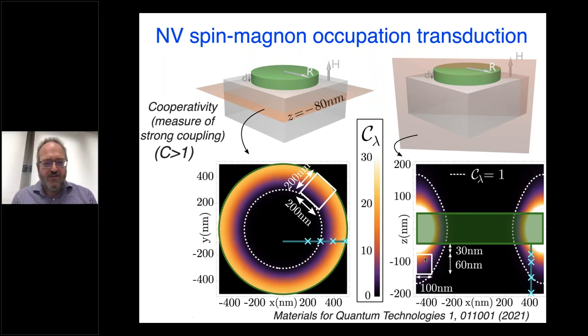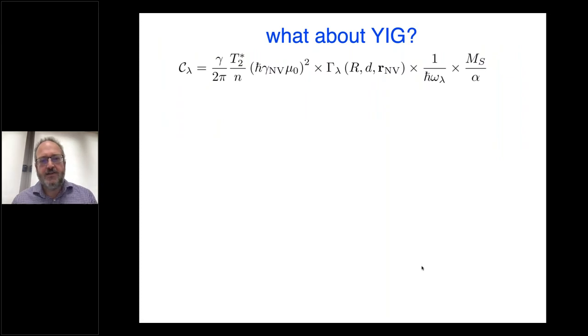Now, we're focusing on this white box down here. The reason for that is that the spin coherence times of NVs get shorter when they get close to the surface. So if we want to avoid that problem, we'll consider NVs that are 30 nanometers or more below the surface of diamond. And there's a range of accuracy for implantation of nitrogen if you want to make implanted NV centers. With a very conservative estimate of that, 100 nanometers wide, 60 nanometers tall, this gives us a large region where the cooperativity is much in excess of 10. So we can expect cooperativities on the order of 15 or 20 in such a system, which means we should get pretty good fidelity for NV to magnon mode occupancy transduction.